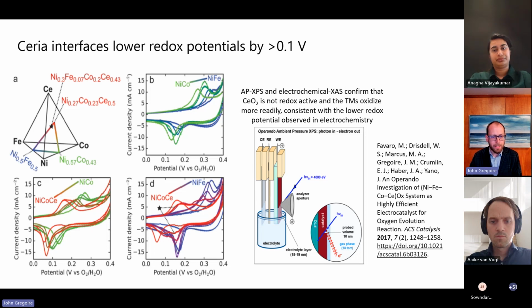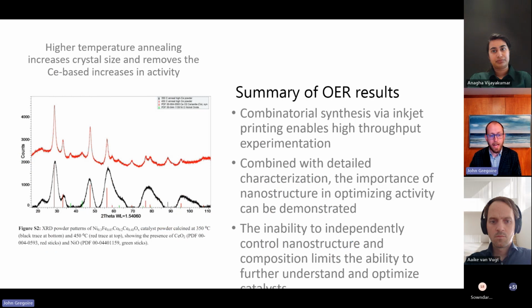The other part of that story is if you anneal these same printed materials at higher temperature, you destroy that fine nanostructure. You grow the grains, and you have much fewer boundaries between the mixed transition metal oxide and the fluorite ceria, and the improved overpotential at low current density goes away. So this shows a successful implementation of high throughput techniques to screen a number of compositions in a high order composition space that would very much not be amenable by traditional means. And the inkjet printer is fantastic at doing that.